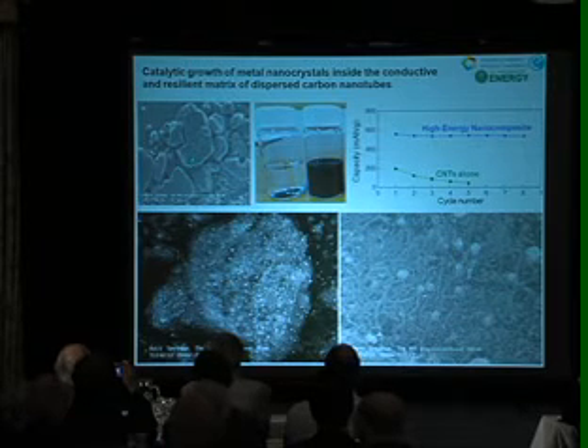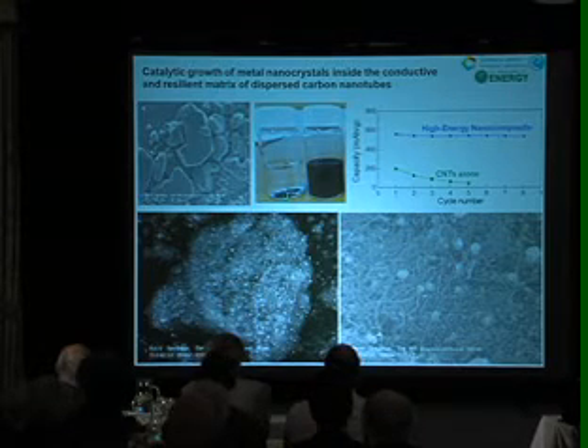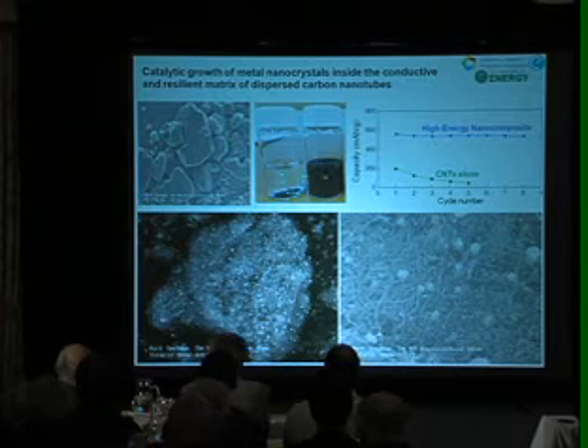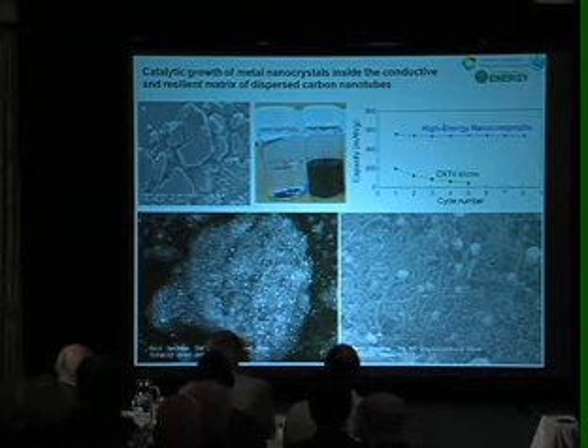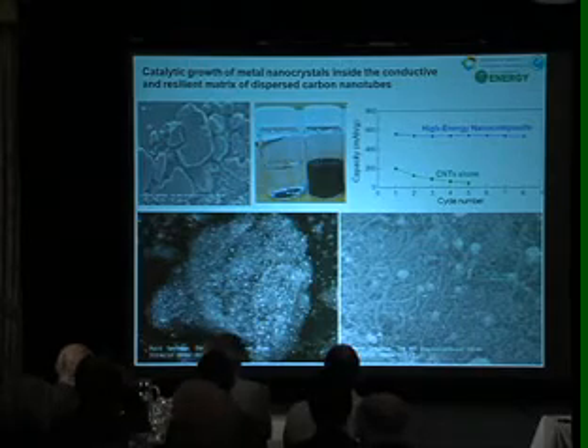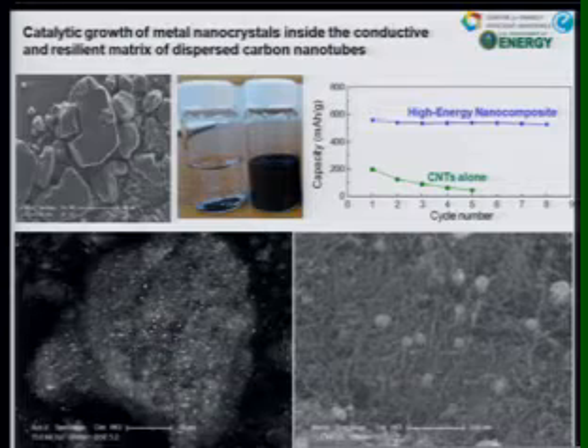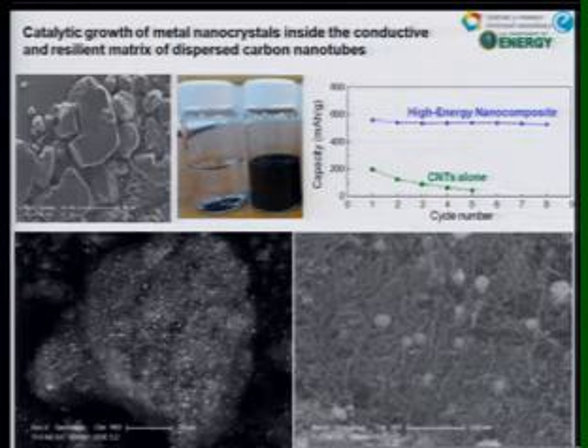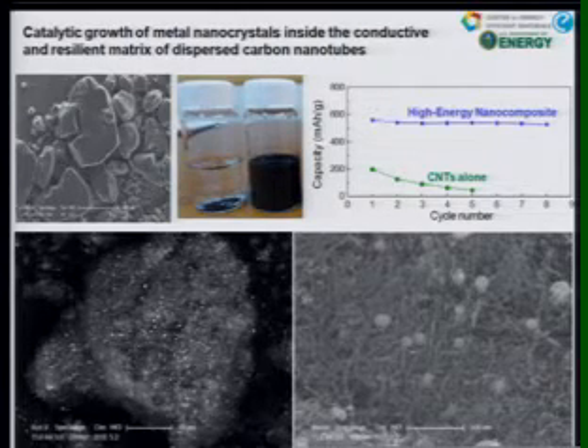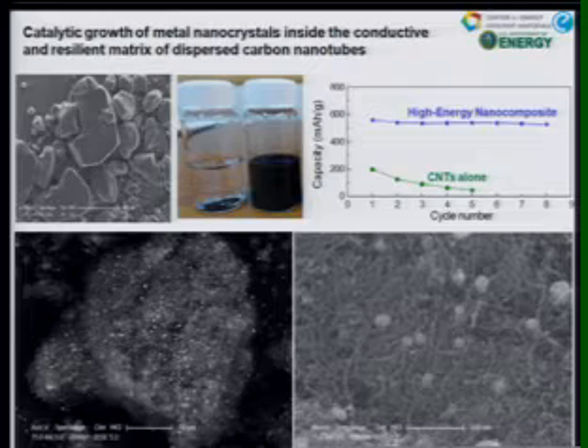The carbon nanotubes, as made inexpensively, are agglomerates that look like chimney clinker. And they don't dissolve in any solution. But we found ways of dispersing them. And using these dispersed particles now of highly agglomerated carbon nanotubes, you can see the forest of these agglomerated nanotubes here. We again use our catalytic synthesis method to grow tin nanoparticles in situ inside the interstices of this compliant and conductive matrix. And the result here is an even higher energy density nanocomposite.